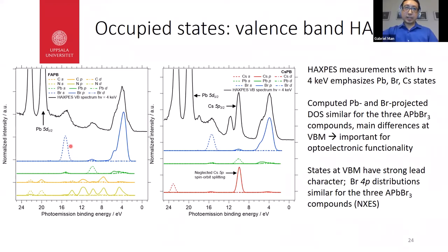The DOS calculations for the bromine states in blue and the lead states in green look pretty similar for the two different compounds. But the main difference seems to be near the valence band edge over here. Since our X-ray emission spectra told us that the bromine 4p states are pretty similar, this strongly suggests that these states are mostly lead character. And the differences near the valence band edge are actually pretty important for optoelectronic functionality, because the band edge states often participate in optical absorption and emission.